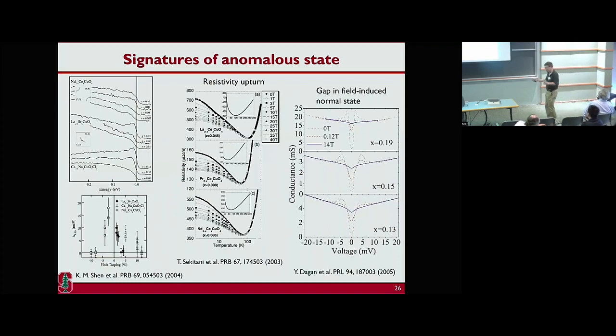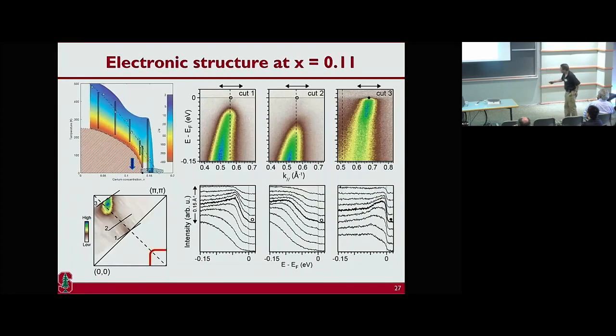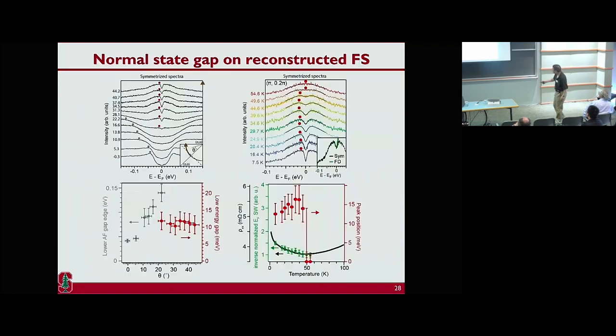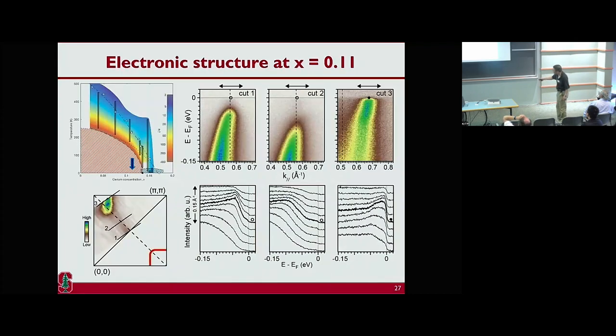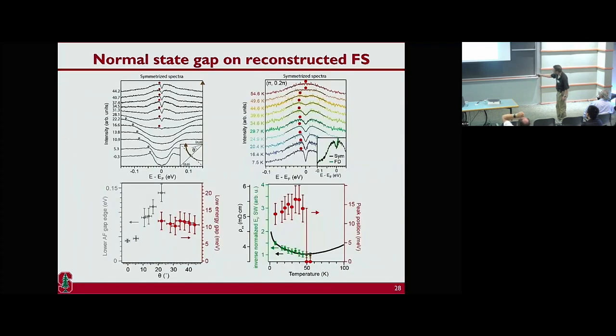More interestingly, Rick Greene's group have shown that, in fact, these systems have a gap, and that gap goes away when you turn on a magnetic field. And they sort of attribute it to the possibility of superconductivity in this long-range ordered state. I'm going to just rush through it. You can see that's the Fermi surface for 11% doping. This is a sample with a long-range magnetic order, and you see these features. The key here is that's the Fermi surface pocket at the antinode. If you look here, you can see there's a low energy excitation, and it's always gapped. And it goes away at a temperature somewhere around 40 or 50 Kelvin. And you can see that this temperature is actually quite consistent with the upturn of the resistivity.